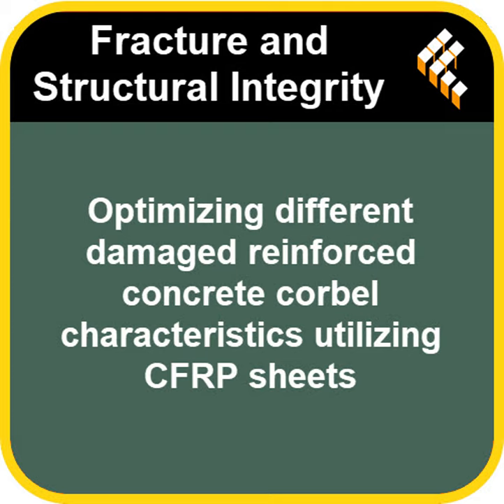But what about the damaged ones? Did stiffness improve there too? It did, but there was a clear trend. As the level of pre-damage increased, the stiffness improvement decreased. Makes sense intuitively. For instance, side-wrapped corbels damaged at 50% saw about a 38% stiffness increase. But at 70% damage, that improvement dropped to around 24%. Still an improvement, but less dramatic.